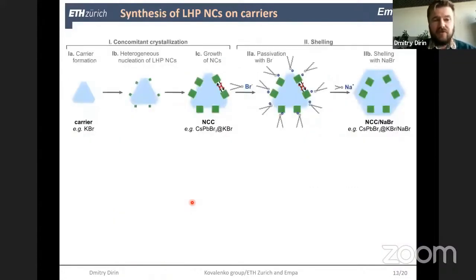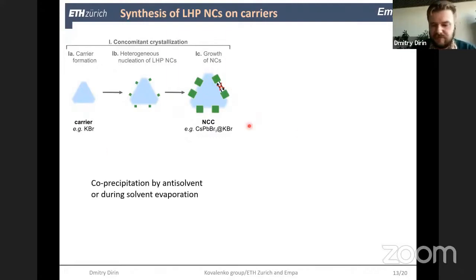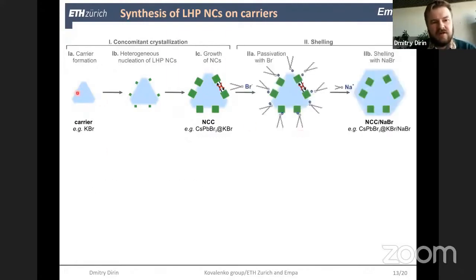So, how do we do this synthesis? First, we create conditions in which we have first nucleation of our carrier, in this case KBr, and then a heterogeneous nucleation of cesium lead bromide on the surface of the carrier. Then those nanoparticles already cannot merge, and at this point it's a fully inorganic system. We don't have any ligands. And then on the second step,